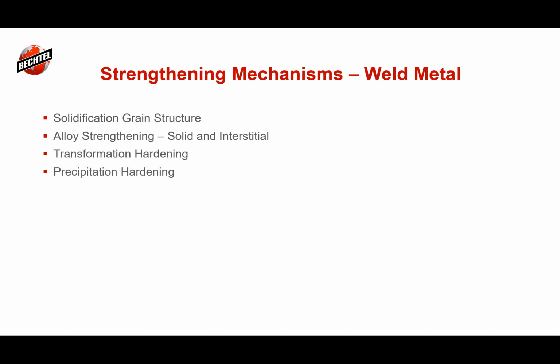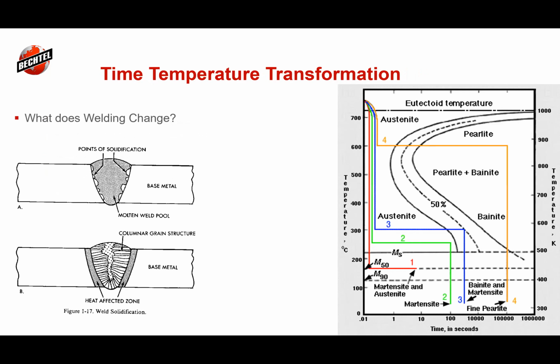Strengthening mechanisms, we talked a little bit about that. I want to focus on the carbon steels for now. When we heat that weld metal up, and the reason why the time temperature diagram is really important is, as we heat this weld metal up, that heat affected zone, we are seeing every possible different raise in temperature in that heat affected zone, and we're cooling down.